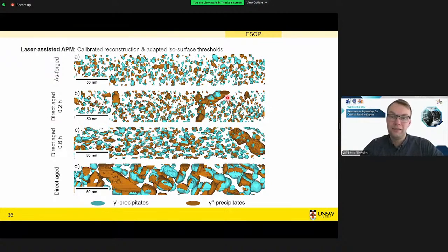We're lucky here in this data set, we captured one of these larger structures, which together with the high resolution TEM, we could show are large gamma double prime particles. After 0.6 hours direct aging, these particles start to grow. And then we have this typical microstructure in the fully aged condition.